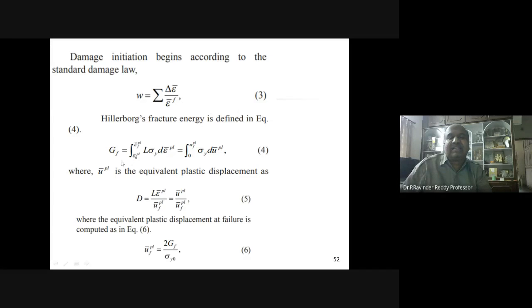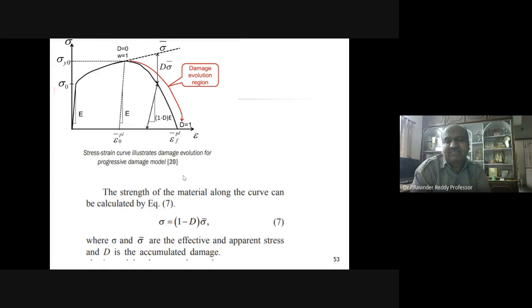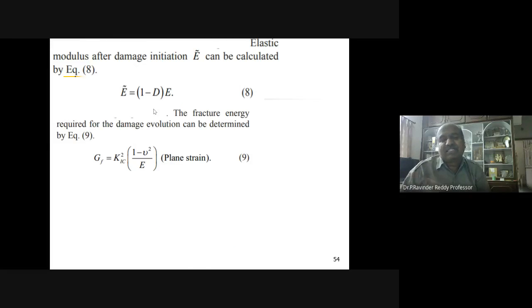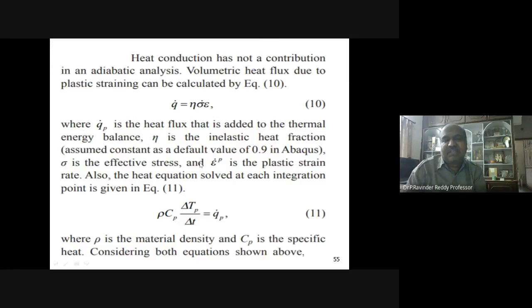So when we calculate the damage and the contact mechanics in the chip and tool contact, automatically these we can select in our Abaqus model. Then the failures can be estimated, and the pattern of variation, the progressive damage, especially since this is going to be a chip model. So for the chip and work, and chip and tool, only that portion we are going to have as a localized fracture model. So for fracture and contact, when you connect the thermomechanical and mechanical structural analysis, we need to include these terms. So how the elastic modulus decreases? We know the theoretical equation, the strain energy release rate with the stress intensity factors for plane strain and plane stress, with small variation.